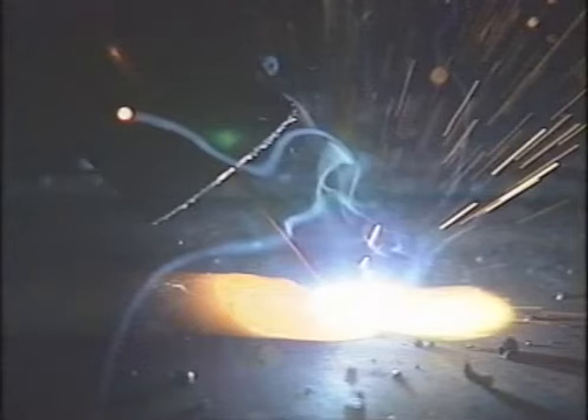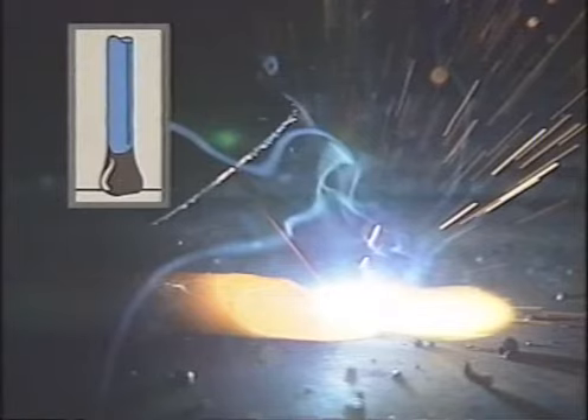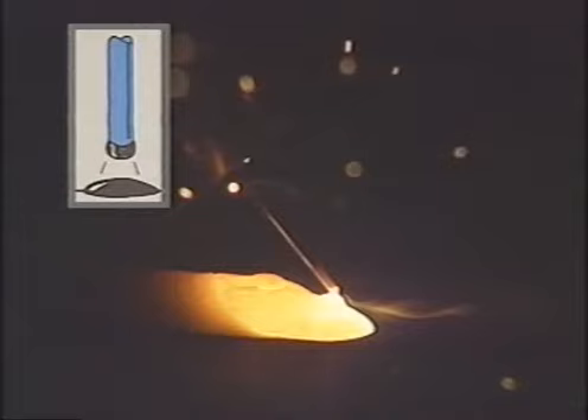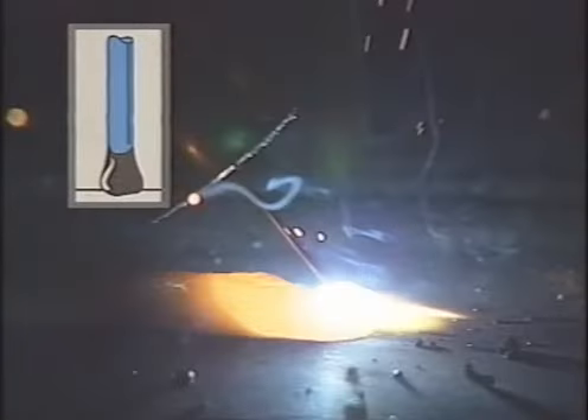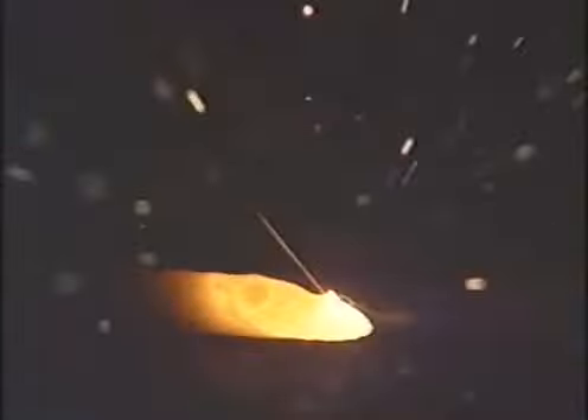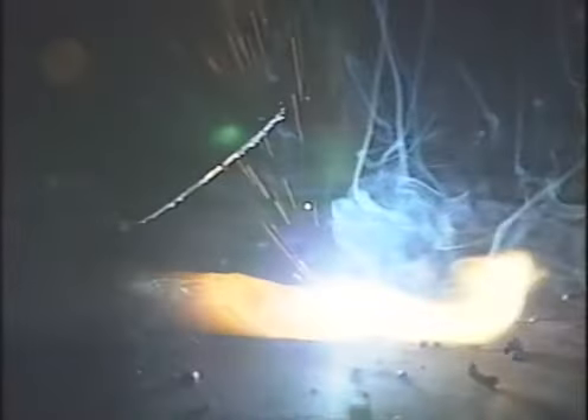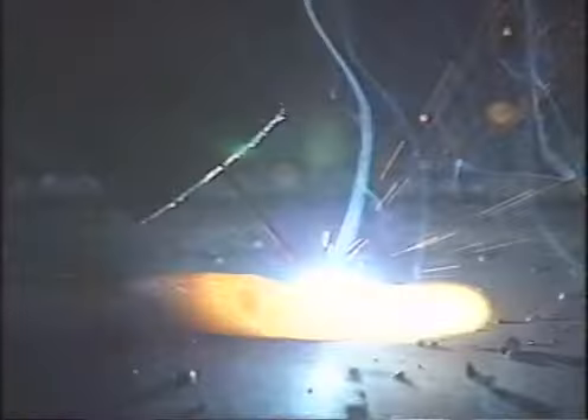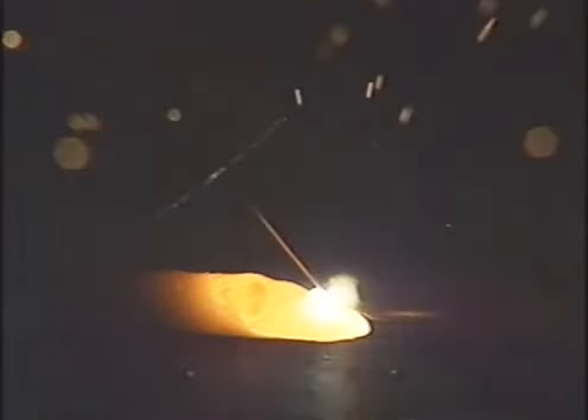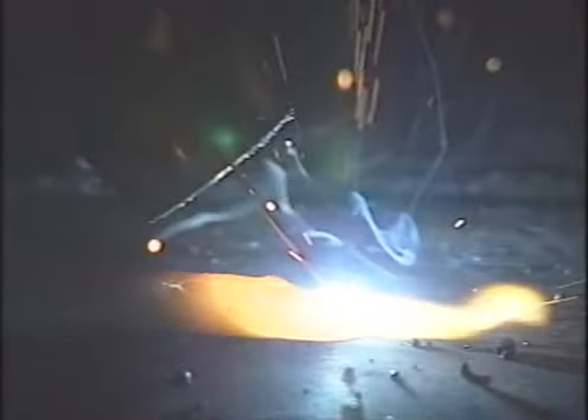The short arc or dip transfer method requires low current and voltage settings to produce a short-circuiting arc. The short circuit occurs when the electrode wire actually dips into the weld pool. When the electrode wire has melted off, it again dips into the weld pool, recreating the short circuit. The dipping process can occur up to 200 times per second. This method creates low heat input to the weld area, which is ideal for welding thin metals.